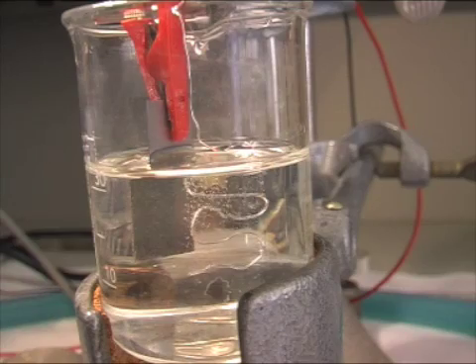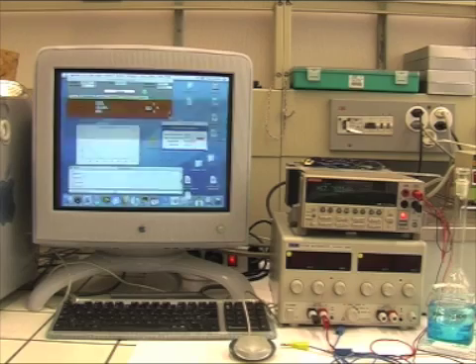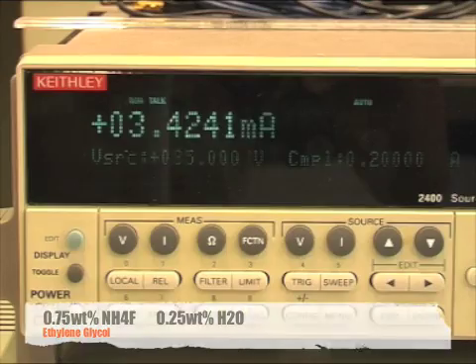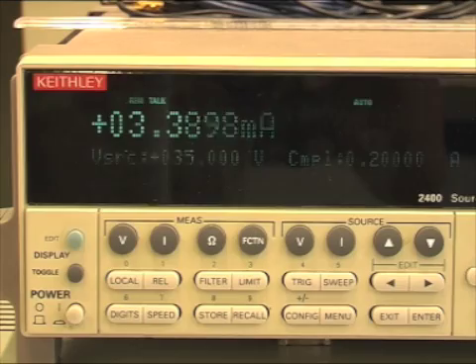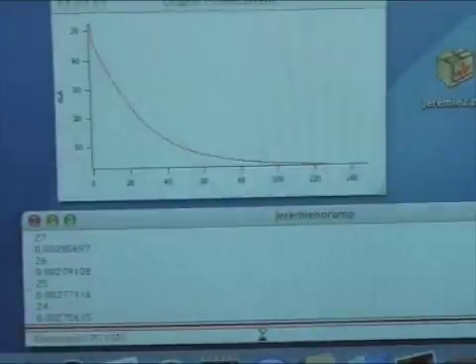The nanotubes were made by potentiostatic anodization of a titanium foil in a fluorine-containing electrolyte at 35 volts at room temperature, with time depending on the desired thickness of the film.